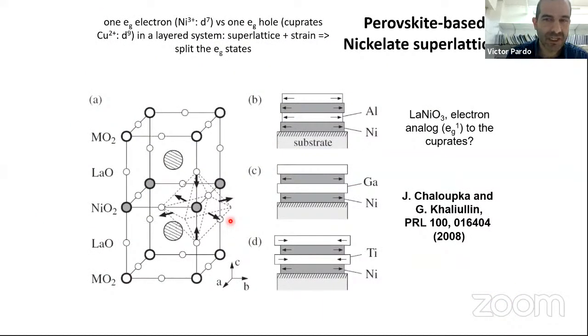Another not so successful possibility was proposed by Chaloupka and Khaliullin a few years ago. They said it's okay, instead of having one hole in the eg states, we can have one electron. This can be attained with, for example, lanthanum nickel O3. This is a nickel 3+ system. It has one electron in the eg levels.